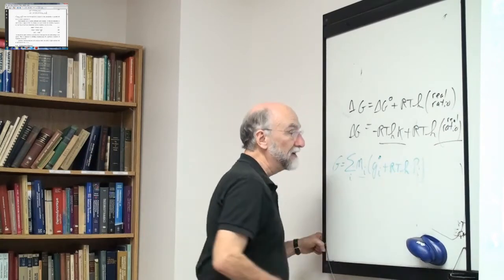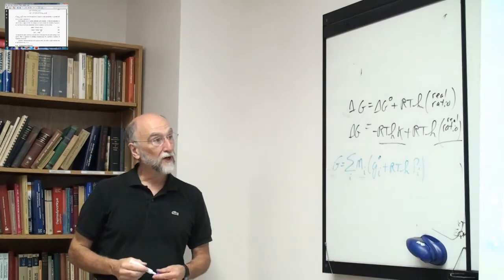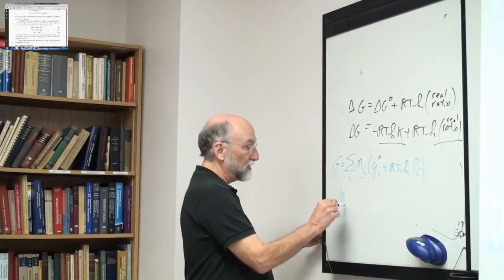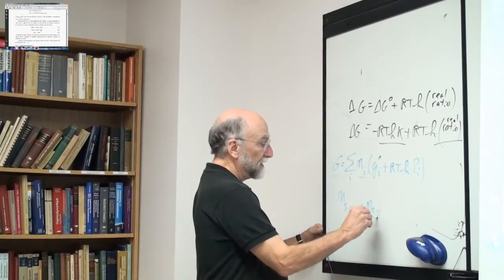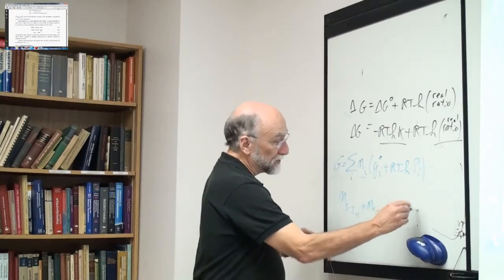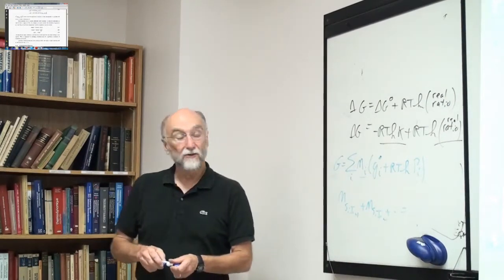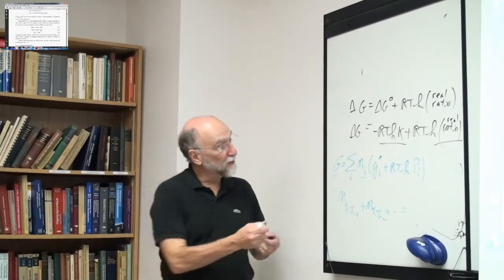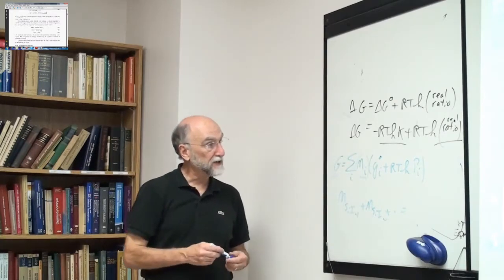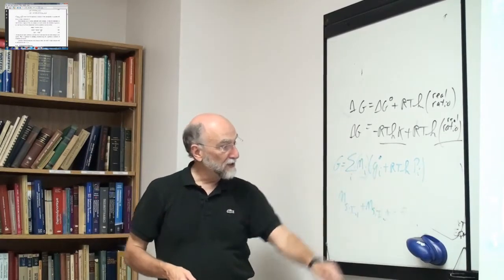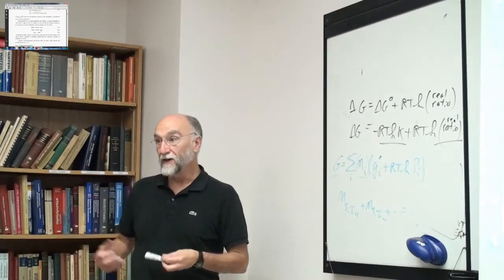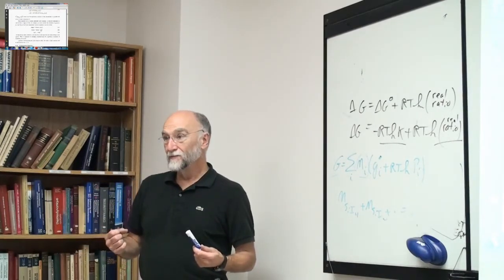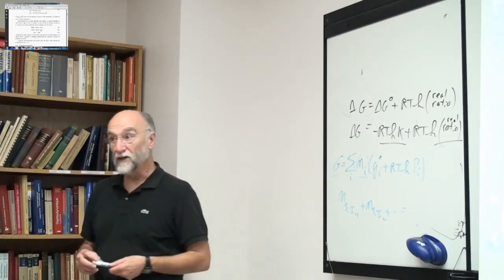You have to do this subject to the mass balances, that the number of moles of silicon tetraiodide plus the moles of silicon diiodide, etc., equals the total number of moles of silicon in the system. So you find the number of moles of each particular species that minimizes the total Gibbs energy, given the mass balance, how much silicon and iodine you have in the entire system. And this is how the Gibbs energy minimizer works.